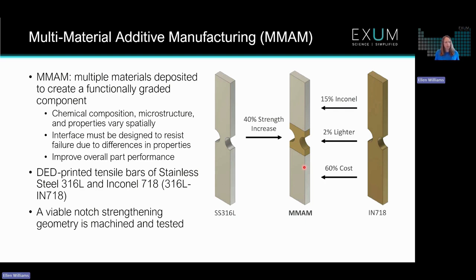This was done through a directed energy deposition, or DED, printing process that uses powder and a laser to deposit. And essentially what was done is, from the bottom up, we've gone through layer upon layer of stainless steel, then switching to that nickel superalloy, then switching back to stainless steel in the build process. And the challenge here is that the interface between those two materials is critical to design properly, because anytime you have two materials that have different properties, different thermal properties especially, that can potentially be a weak point, and that can potentially be where defects occur.